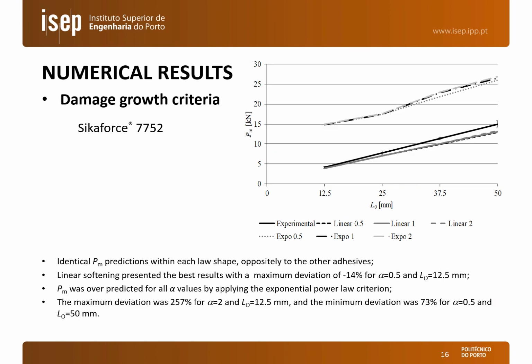And finally, for this damage growth study for the Sikaforce 7752, we have virtually identical maximum load predictions between each law shape, either linear or exponential, but once again the linear softening gives much closer results than the exponential softening. But here we had a minor underestimation of the maximum load, which was up to 14% in this case for an exponent of 0.5 and an overlap length of 12.5 millimeters. On the other hand, we had major offsets for the other laws.